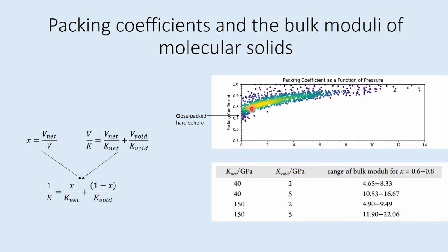If we use ionic radii for those instead of van der Waals radii, the fitting tends to look a lot more classical and falls into that thicker range. So I think it's perhaps a misuse in those particular instances that could give that anomalous behavior, but it's a case by case basis trying to work out why.